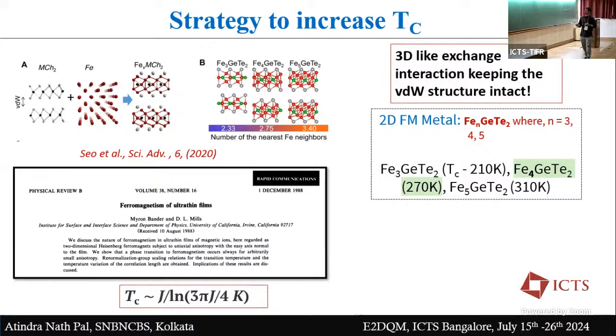The interesting aspect is that the TC has increased very much compared to the other van der Waals materials, where other materials have a TC around 100 Kelvin or below. In this case, you can already see 210 Kelvin for the first one, Fe3GT. Then the second one discovered was Fe5GT at 310 Kelvin, already room temperature. What we are focusing on here is Fe4GT2, where the TC is 270 Kelvin, near room temperature.